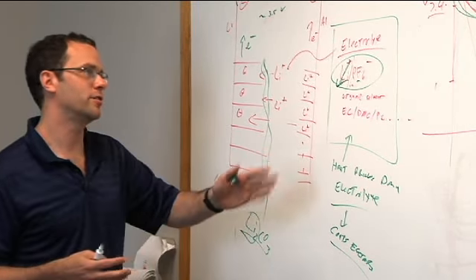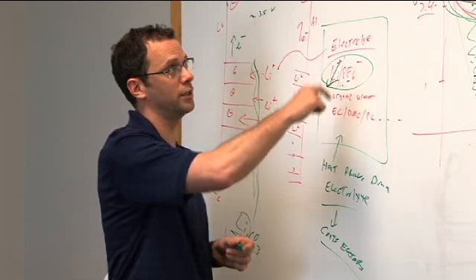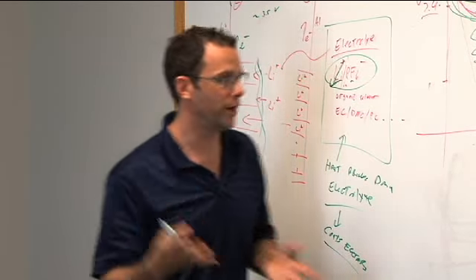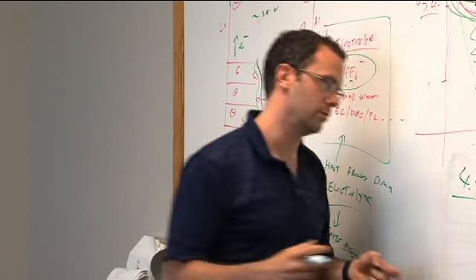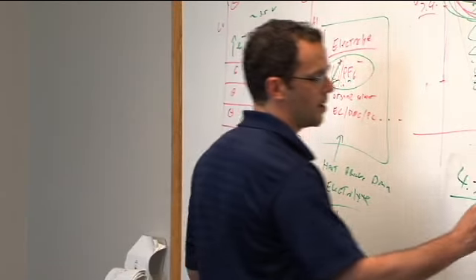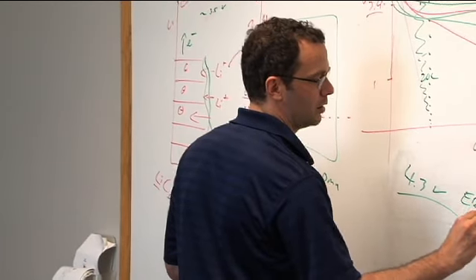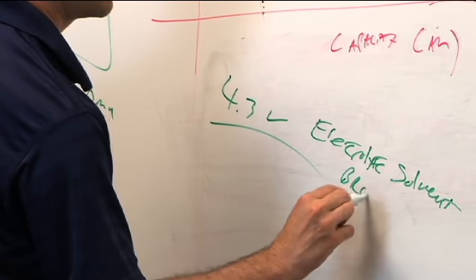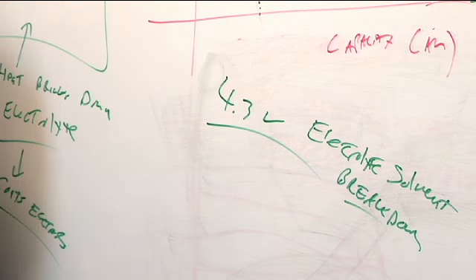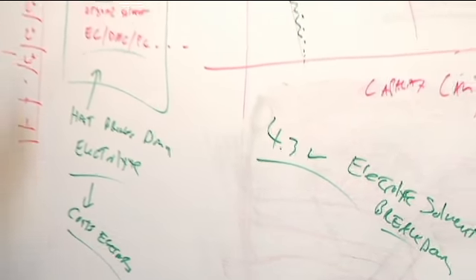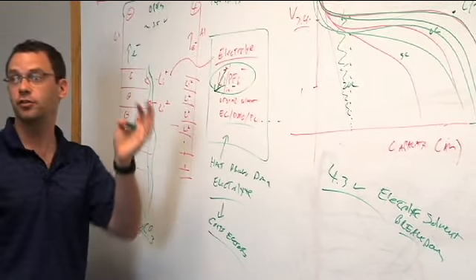Okay, so the cathode in this case is totally stable. So the only enemy for this particular chemistry is the breakdown potential of the electrolyte itself. That's about 4.3 volts, right, or so over the long term. You can go higher, but above 4.3 to 4.4 volts, you start to see electrolyte solvent, I should specify, breakdown. So this is equivalent to water electrolysis at 1.3 volts, right? Whatever this solvent is, it starts to split somewhere between 4.3 and 4.5 volts. It will just start to evolve into gas, right?